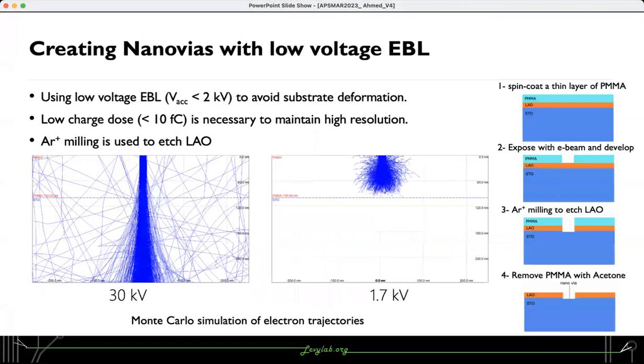The method we use to create these nanovias is low voltage EBL, which comes with merits and limitations. The advantage over the conventional EBL is that highly accelerated electrons that stop in the substrate cause non-recoverable mechanical and electronic damage, and this helps in avoiding this. However, low acceleration voltage limits the usable charge dose to small values due to the increase in the scattering cross-section compared to high acceleration voltage. Following the e-beam patterning, we use argon ion milling to etch the lanthanum aluminate.